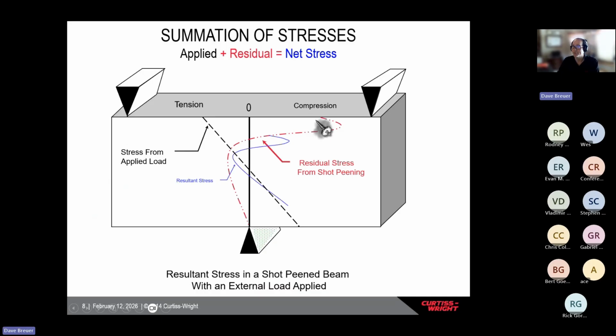That's this curve here. What we're showing is that even under peak load - this is the tensile stress - there's a higher magnitude of compressive stress, such that the surface is still in a net compressed environment even at peak load. Theoretically this part should never fail, but in reality it's probably going to last 3 to 5 to 10 times longer by the residual stress canceling out the applied tensile stress.